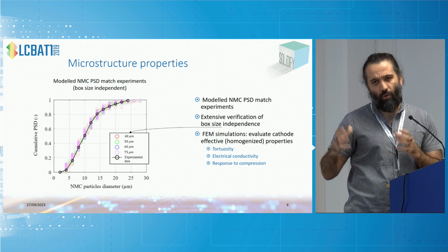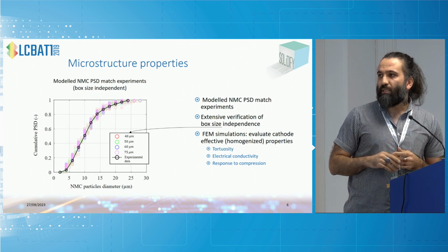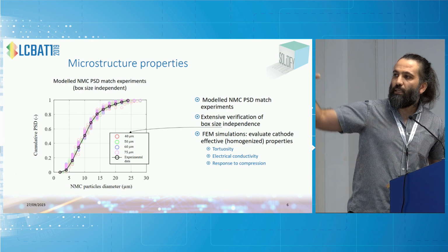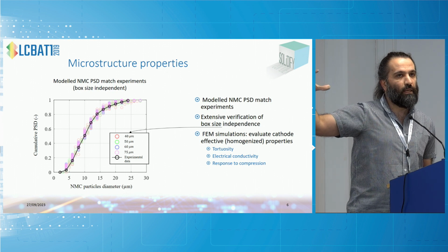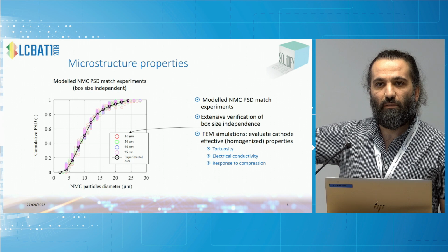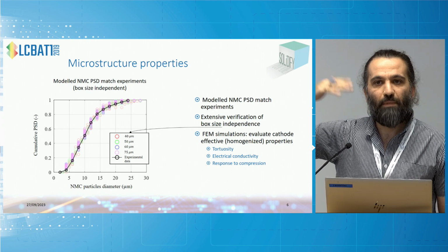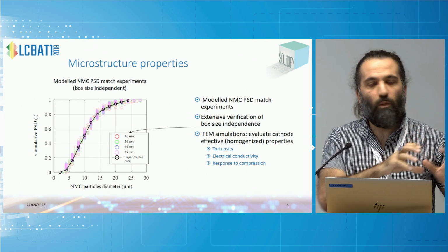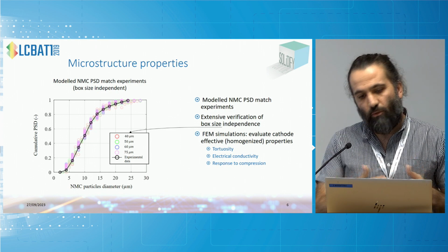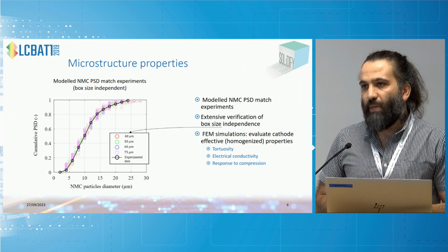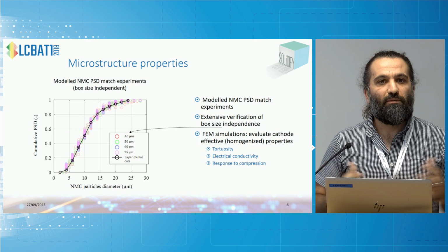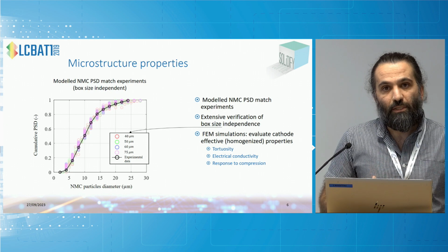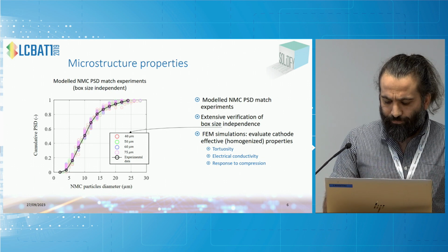And that's very important, because at the end it impacts the effective properties of your porous electrode. Simply speaking, tortuosity in a bulk way of thinking, but we can also look at it locally. Tortuosity, of course, impacts the effective conductivity, ionic conductivity, and everything. And even in this case, impregnation of the electrolyte.